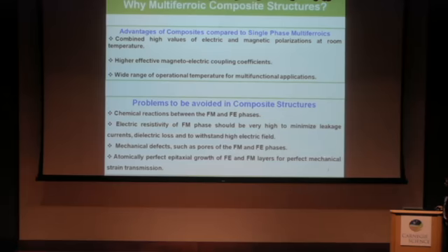During the synthesis of composites, with the ferromagnetic and ferroelectric phases, we have to take care of a lot of things. There should not be any chemical reaction between the ferroelectric and ferromagnetic phases, and the electrical resistivity of the ferromagnetic phase should be very high to minimize leakage currents and dielectric loss, in order to withstand the high electric field.